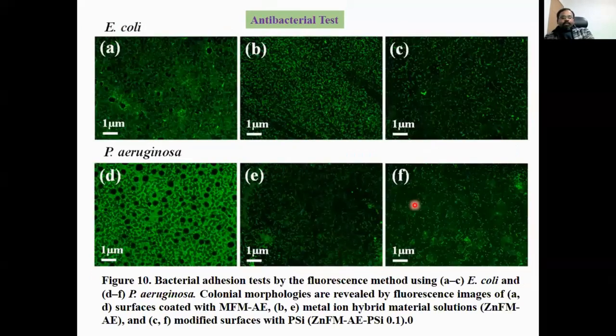And further, we also checked these properties after keeping the samples for 1 minute in a stationary mode. After 1 minute, we checked the transparency again of the coated substrates, which shows that the anti-fogging performance is much better in the superhydrophilic coatings as compared with the hydrophobic coating. Further, we checked the antibacterial properties of these coated materials.